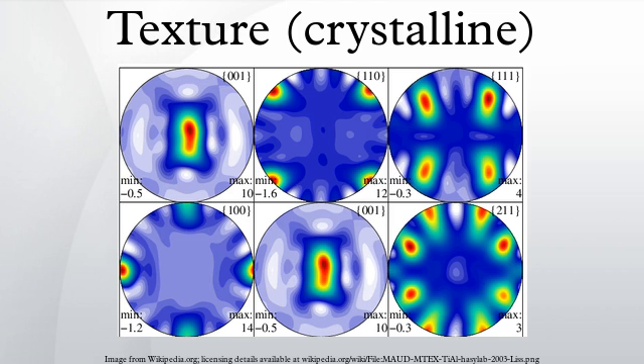However, cold work destroys much of the crystalline order, and the new crystallites that arise with annealing usually have a different texture. Control of texture is extremely important in the making of silicon steel sheet for transformer cores and aluminum cans.